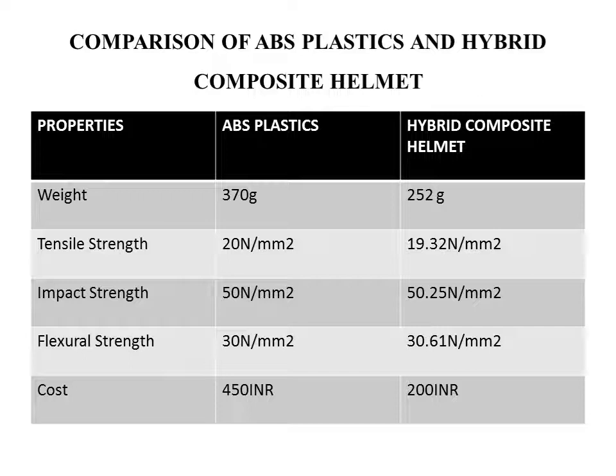And the impact strength of the ABS plastic is 50 Newton per mm squared and the hybrid composite helmet is 50.25 Newton per mm squared. Flexural strength of the ABS plastic helmet is 30 Newton per mm squared, but our composite helmet is 30.61 Newton per mm squared. Cost of the ABS plastic is 450, but our composite helmet is 200. It is a reduction of 250.